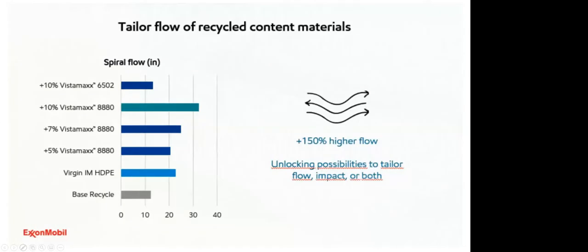In our first example here, we show how our very low viscosity grade, Vistamaxx 8880, can improve the flow of recycled streams. The graph presents the spiral flow test with several recycled formulations coming from post-consumer high-density polyethylene bottles, and also compares it with the flow behavior of virgin high-density polyethylene for injection molding.